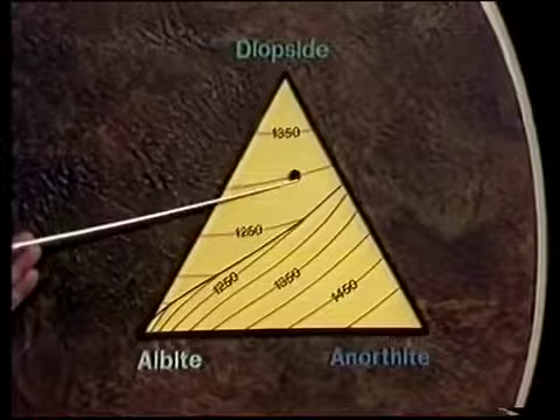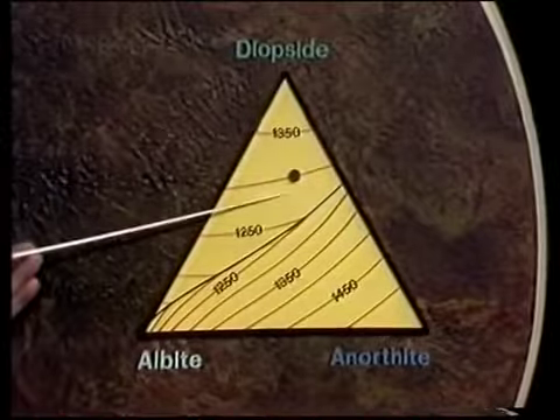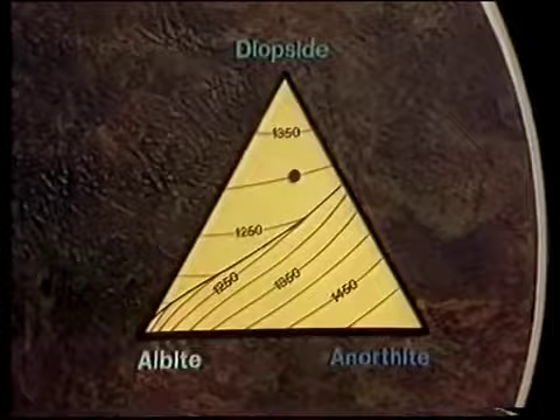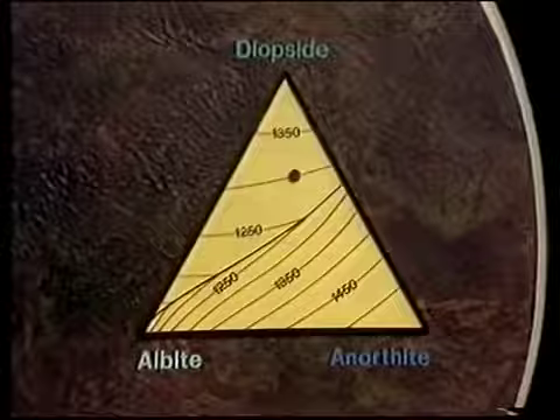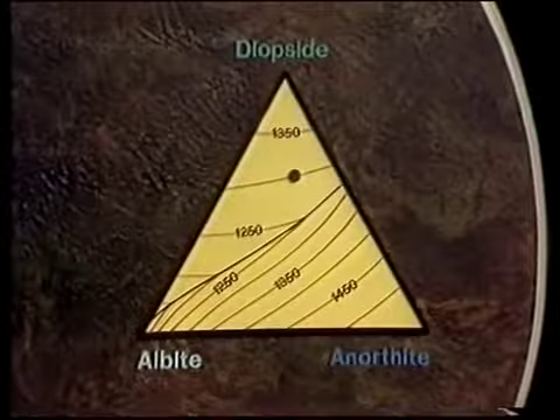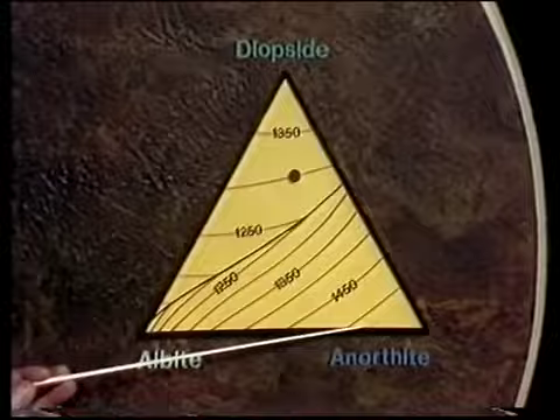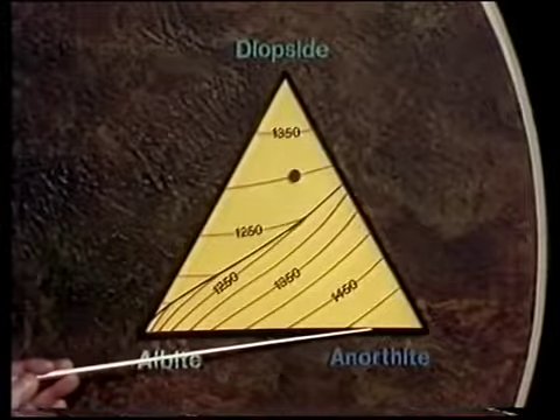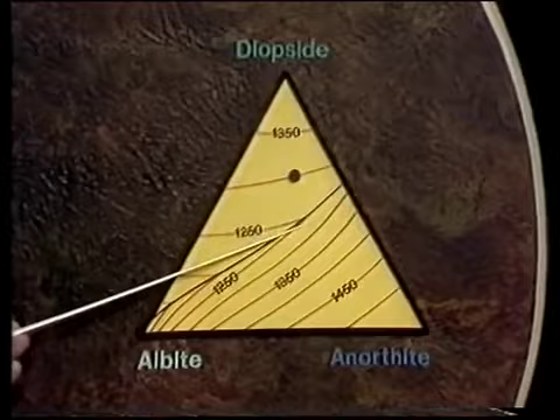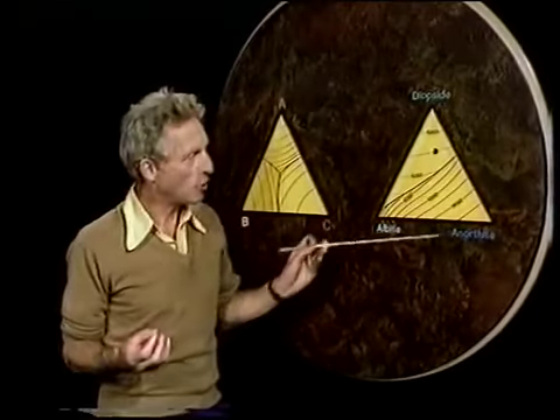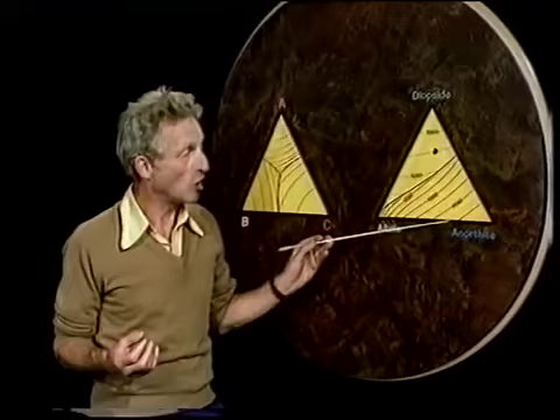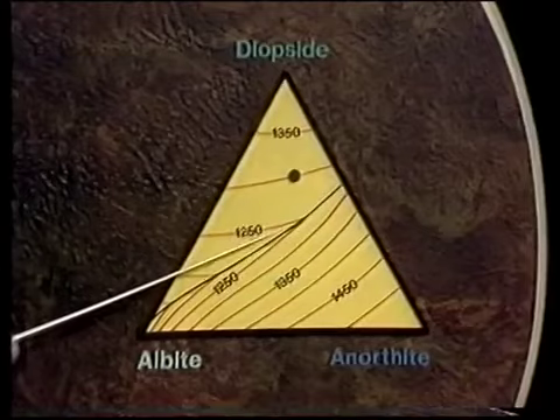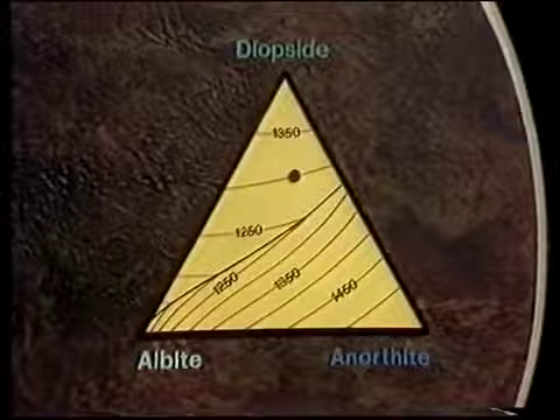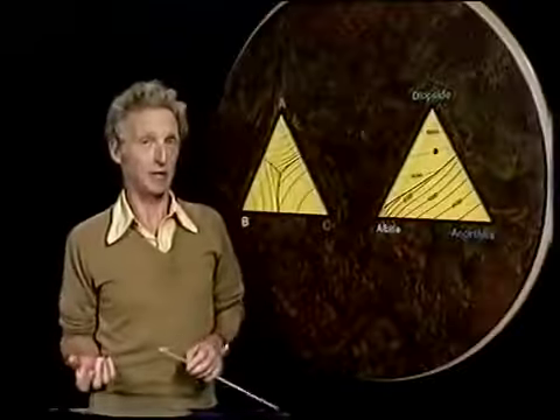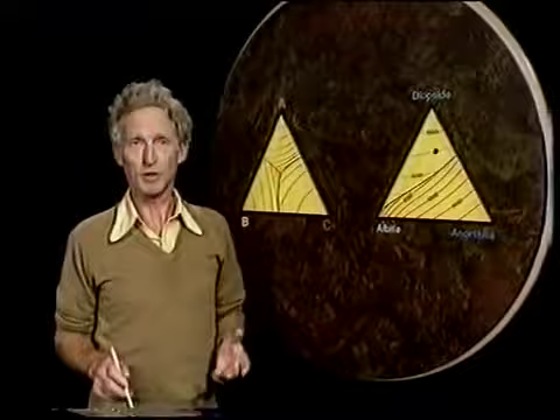Well, now let's go back to our three-component system and see where we've got to. Well, we've got our melt, cooling and crystallizing diopside and moving on down to the cotectic at this point. Now, we know the composition of the temperature of the melt at that point. And so we can use what we know about the two-component plagioclase system to work out the composition of the plagioclase feldspar on the solidus that's crystallizing from this melt. And we can also work out how the composition of the plagioclase crystals will change along the solidus as the composition of the melt changes down the cotectic with falling temperature. That's really a geometrical exercise, and you'll find out more about it elsewhere in the course.